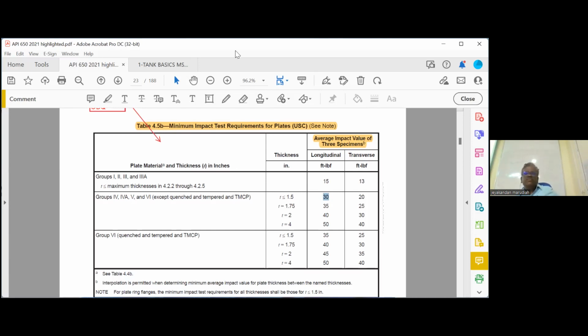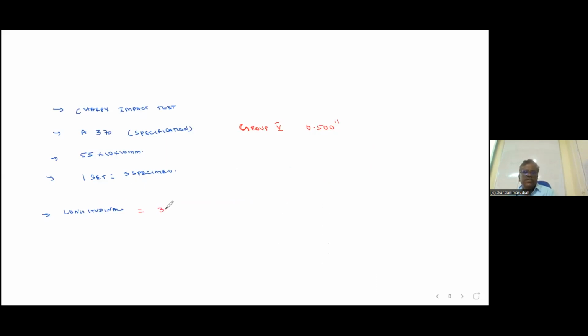Now, the next understanding is very, very important. For the longitudinal specimen, the 30 foot-pounds is called the average of 3 specimens. So the value 30 is called the average of 3 specimens. Then please listen, understand this one. What is the minimum value allowed? Minimum value is 2/3 of the average. 2/3 of the average is equal to 20 foot-pounds, the minimum for one specimen. So for average, we refer to the table. Minimum value is 2/3 of the average.